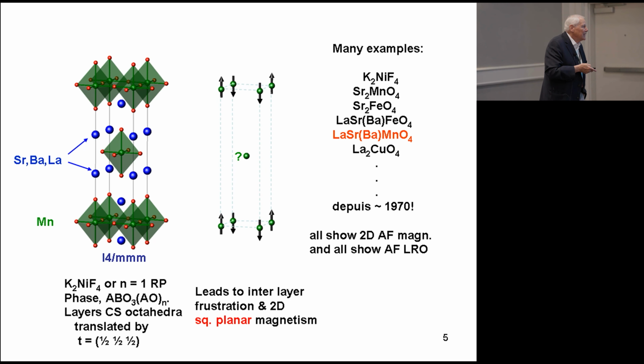Okay, so the so-called n=1 Ruddlesden-Popper phase has been well studied. It crystallizes in the I4/mmm space group. You have corner-sharing perovskite layers displaced by a 1/2 vector. And the large cations can be all sorts of things: strontium, barium, and lanthanum.